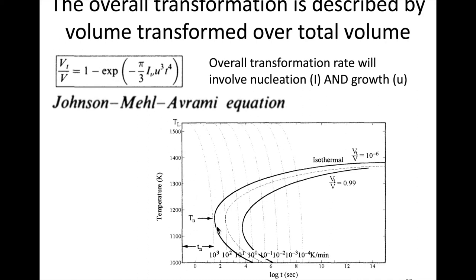This is a strong function of temperature. The highest rates are at intermediate temperatures. Up here at the top right, this is very close to melting. This is log time down here and this is temperature - this is a transformation curve. The nucleation starts at the first line and finishes at the second black line. At the highest temperatures it doesn't nucleate until a very long time, and at really low temperature like 1000, the time it takes to transform starts off pretty slow.